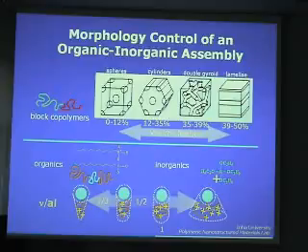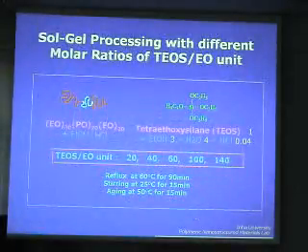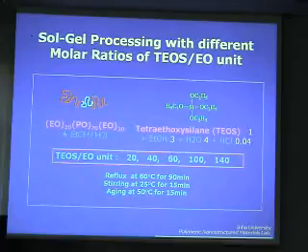So we prepare this solution using the TEOS and the P123 triblock polymer, and we make the triblock polymer solution approximately 38% and mix it with the TEOS inorganic solution, then stir and age it for 15 minutes or a little bit more.